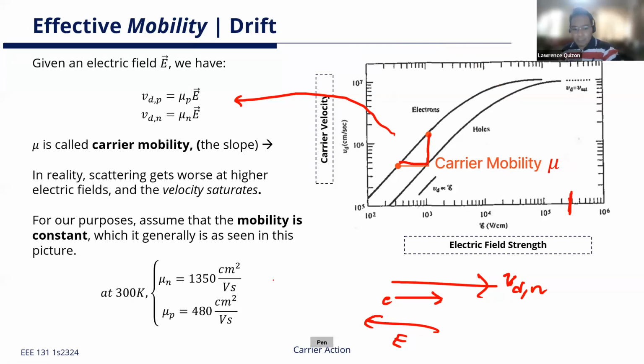All right. Typical values for the effective mobility is this one, no? So mu n at 300K silicon is around 1350 cm squared per volt second. Remember the units, guys, kasi the units are fairly important for you guys to sanity check your calculations, no? It's very important, no? Kasi if you don't remember the exact equations, tas may tinatanong sa'yo, you will be able to derive exactly what you need by looking at the units.